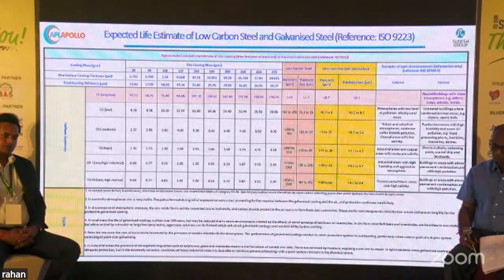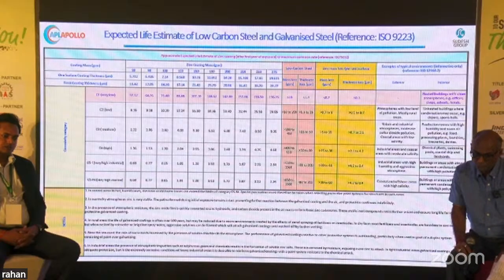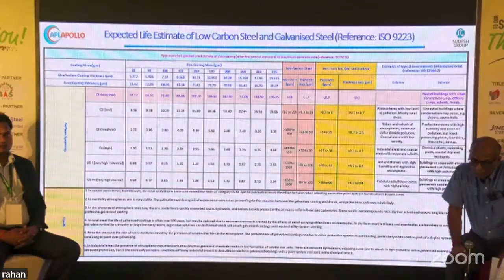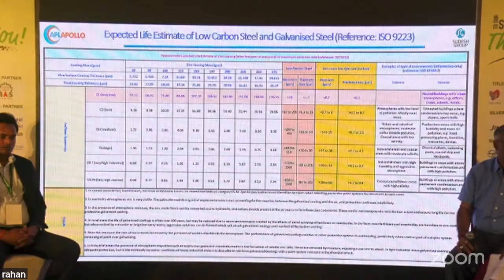Now this is the table as per ISO 9223. The reference shows the corrosion rate of normal steels, and in the yellow color the corrosion rate of zinc is shown. Zinc is almost 20 to 25 times more corrosion resistant than normal steels. That's why it protects the base metal and enhances the life of the structure.